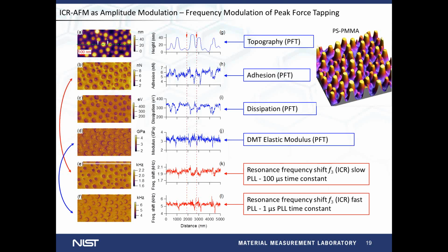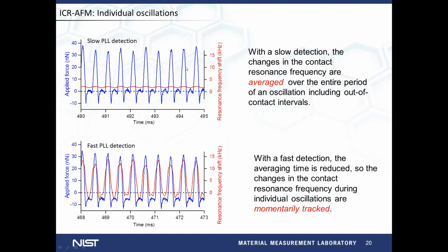The explanation is that with the slow PLL, in the maps that we acquire, we basically get the average value. With a slow PLL, because the time constant is increased, we also average a lot over the out-of-contact regions, and this gives us more contribution from the adhesive forces. This is why it correlates better with the adhesion map. However, with fast PLL detection, we are able to better track what is going on momentarily with the resonance frequency. Here is better evidence for this explanation, where we recorded successive taps by high-speed data capture with both slow PLL and fast PLL detection.